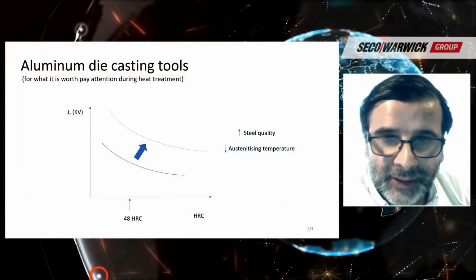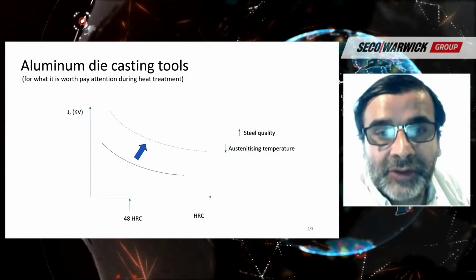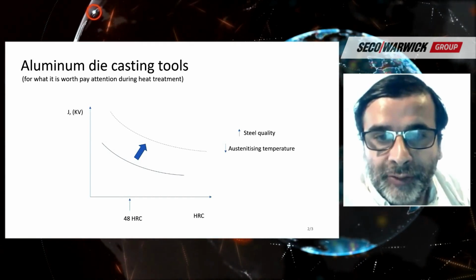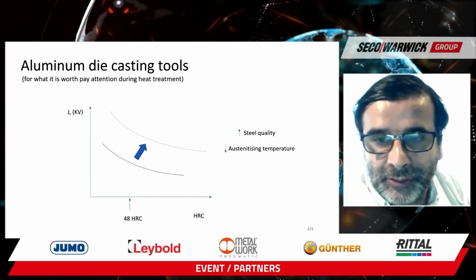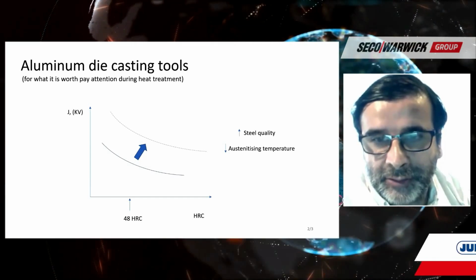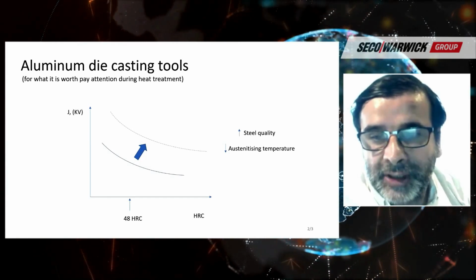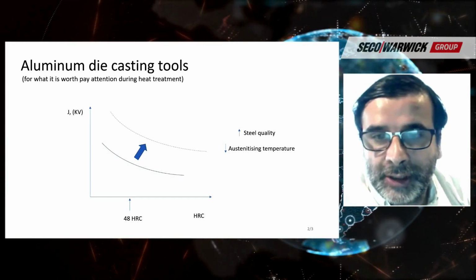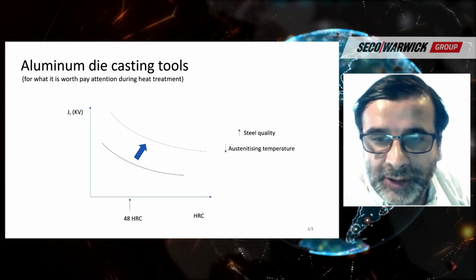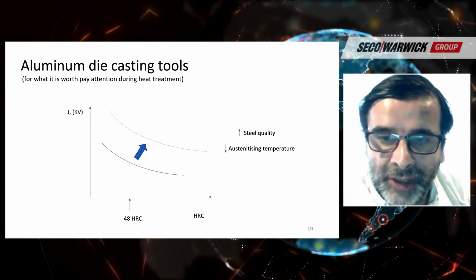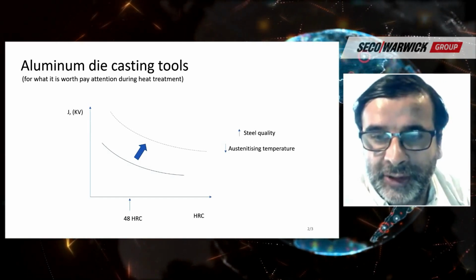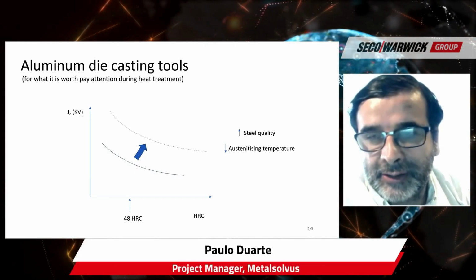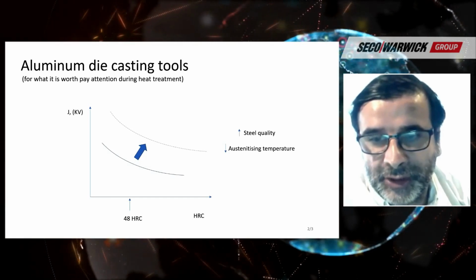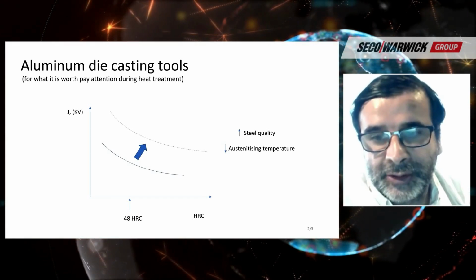And for that we should take a look at the relationship between toughness and hardness. This is related, as we see in this slide, but we can improve it by changing the steel grade to a remelted grade, for instance, or if we are speaking about heat treatment, we should look for a lower austenitizing temperature. This will give a finer microstructure, and a finer microstructure will lead us to improved toughness of the material for the same hardness. Yes. This is important to take into consideration when we are heating up the material.